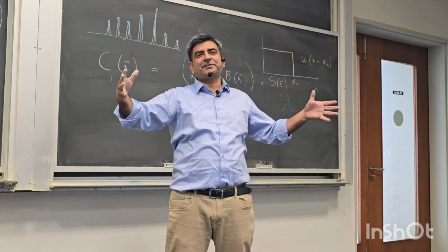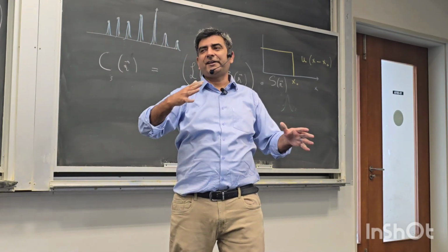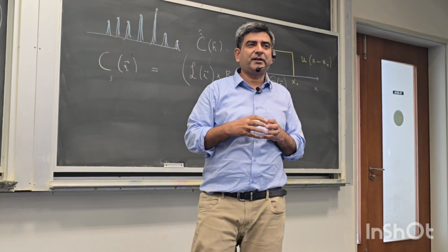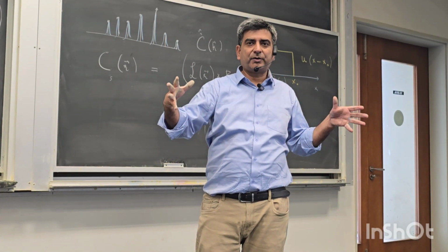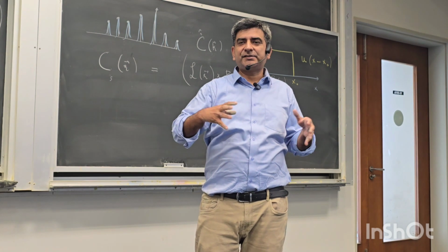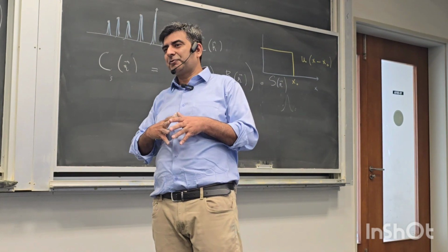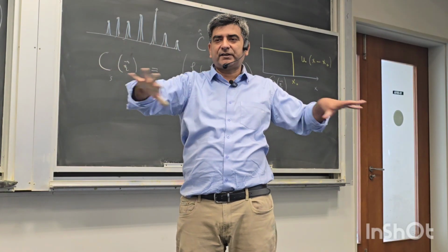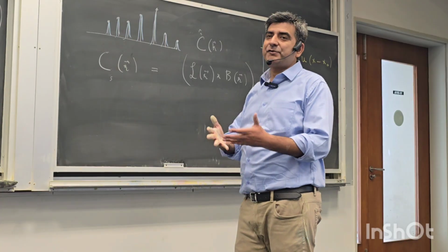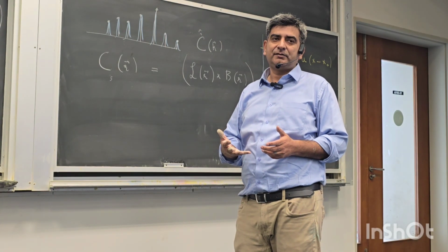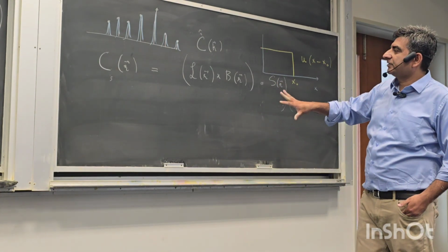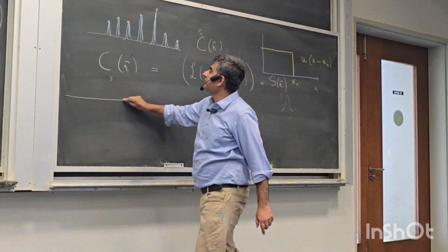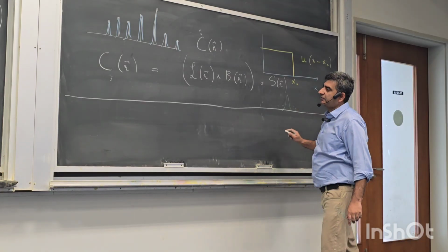If you have a big crystal, with a lot of crystallinity and no grain boundaries, you'll get very sharp peaks. So smaller size nanoparticle X-ray diffraction gives you broader peaks, to the extent that for an amorphous material, which does not show any crystallinity, you just get a broad bump. No peaks are seen. For liquids, you can do X-ray diffraction as well. So this is the Fourier description of the lattice and the structure. Now let's move on to diffraction and relate this to diffraction itself.